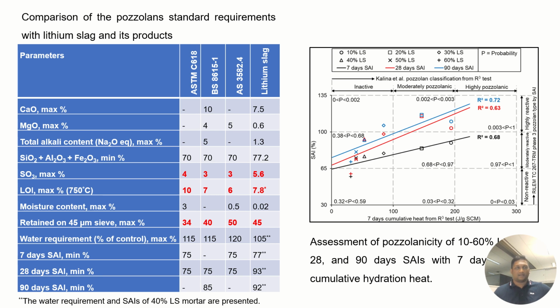The particle size is a little bit coarse, 45 micron, which is higher than the requirement for the ASTM and BS standard. Other than these parameters, the strength activity, water requirement and the oxide requirement are fine with all standard requirements. And it is seen that 40% lithium slag incorporated cement mixes provided good strength and good development in strength.